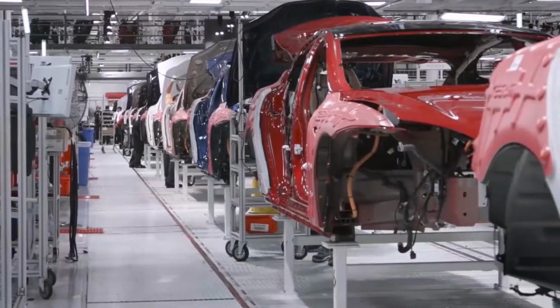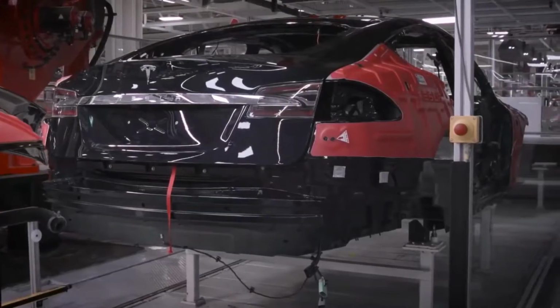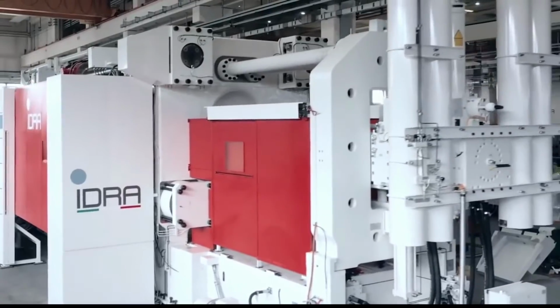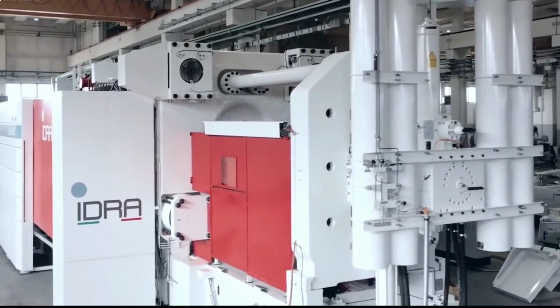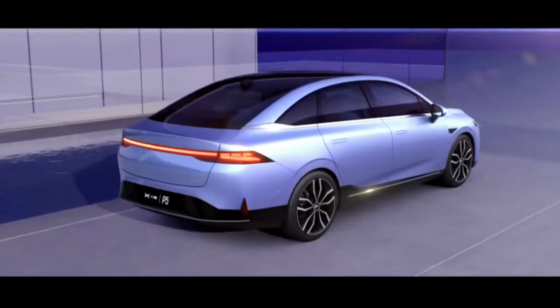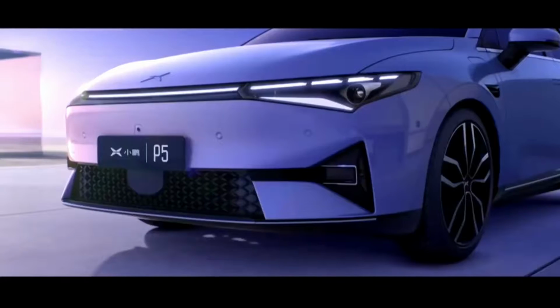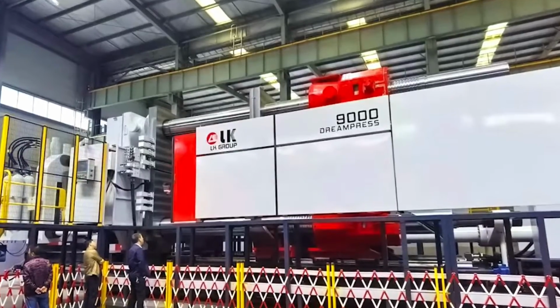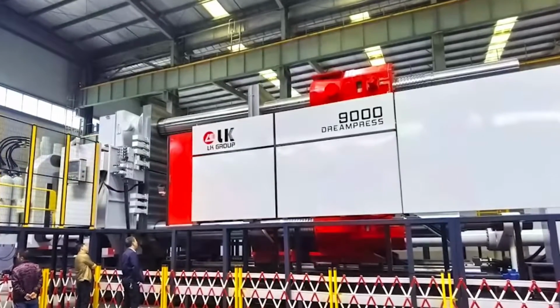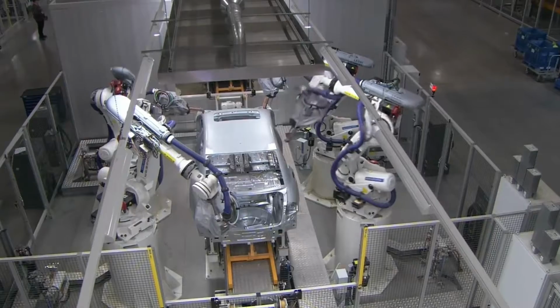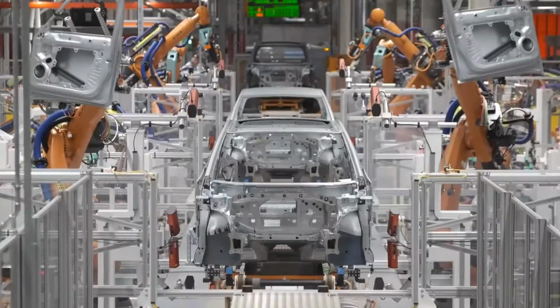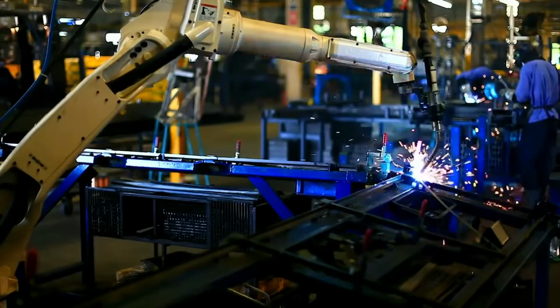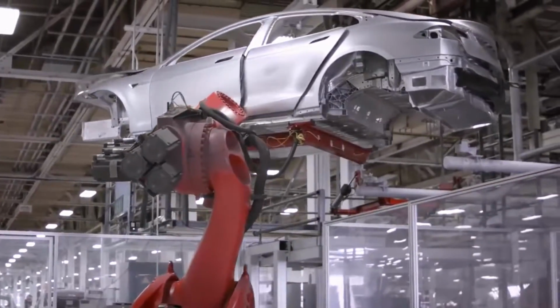A robot reaches in and removes the casting, placing it in a quenching tank to reduce the temperature from 400 to 50 degrees Celsius, 750 to 120 degrees Fahrenheit. A mechanical trim press cuts the approximate edges, with excess aluminum being recycled back into the melting oven. The remaining useful part of the casting is X-rayed to check the internal structure, trimmed by laser, drilled for fittings, and then computer measured for accuracy.